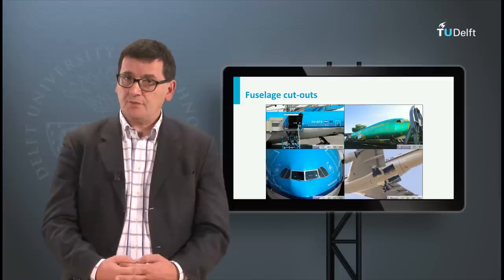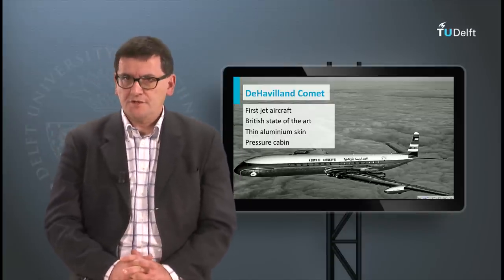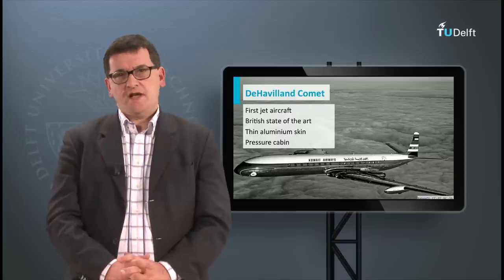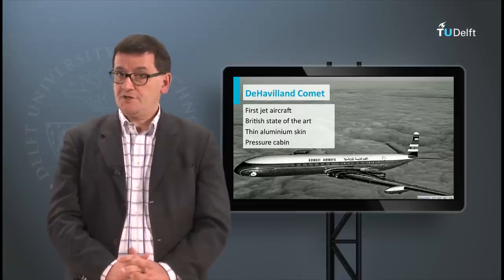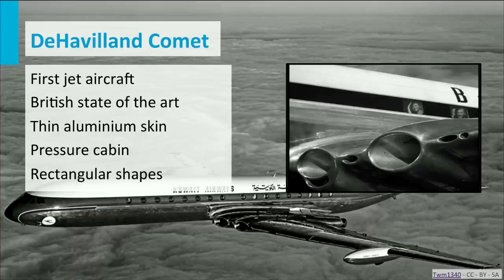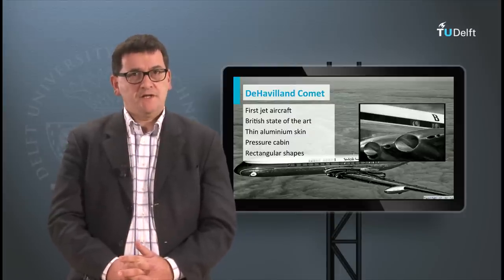The skin thickness has to be increased. Pressure cabins are also related to metal fatigue. After World War II, new aircraft were developed made of aluminium, equipped with jet engines and a pressure cabin. The British de Havilland Comet was the first operational jet aircraft of the new age. Two of these aircraft fell from the sky in the early 1950s and nobody could tell why. After grounding the aircraft, a thorough investigation proved that metal fatigue in the rectangular window shapes was the cause. Up to that moment metal fatigue was underestimated, and due to some unfortunate design choices the Comets fatigued and failed during flight.